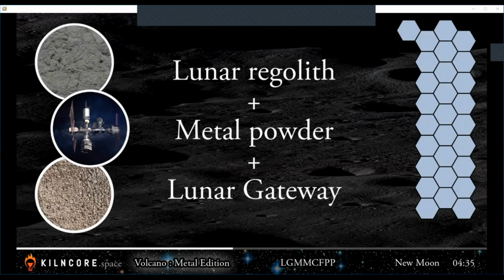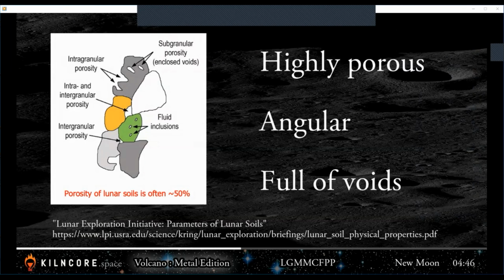We proposed the partial fusion of lunar regolith, mixed with a bit of metal powder, in a reduced gravity environment to mass manufacture hexagonal molten metal ceramic filters. Lunar regolith is highly porous, is very angular, can hook to itself, and is thus partly self-supporting.